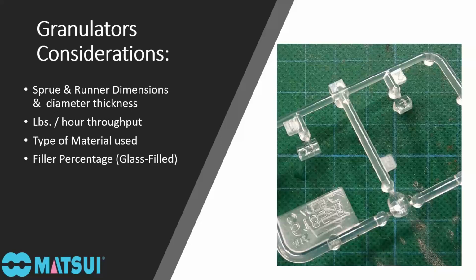So things to consider if you're going to be wanting to granulate or use regrind would be, what is your sprue and runner dimensions? What are the biggest sprue and runner and or defect parts that you would be grinding up? Not just the width and the length, but also the thickness of the runner. The pounds per hour rate, or what's your cycle time? How many sprues are generated per minute, per hour?